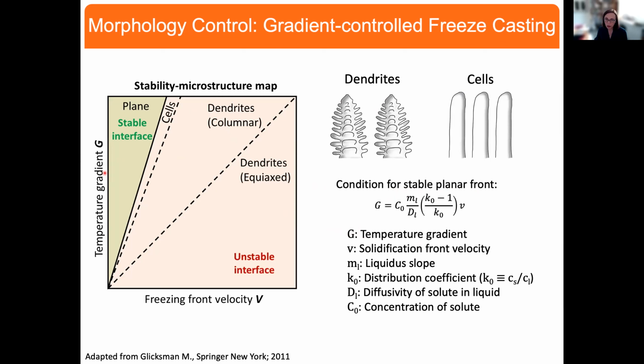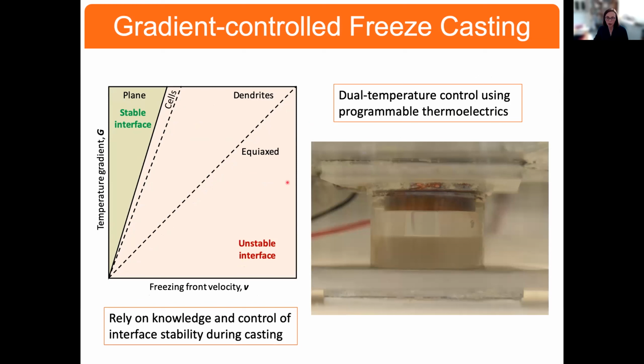Certainly the temperature gradient, that temperature difference between the cold plate and the exterior. We see the velocity plays a role here, the freezing front velocity. But then there are other features in terms of the diffusivity of the solute in the liquid, the concentration of the solute that also plays a role in the system, and that would allow you to move from this stable interface to a cellular interface to a dendritic interface.